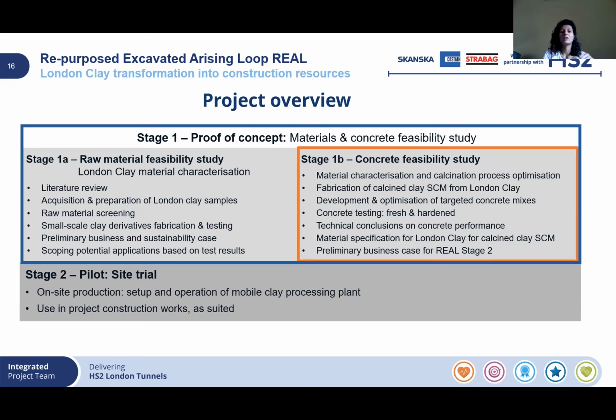And during that stage, we tested several samples of London clay with regard to the material characteristics and whether they would actually constitute good source for calcined clay. So we tested around about 10 samples from across the stretch, and got pretty promising results, which allowed us to move into the stage 1B that